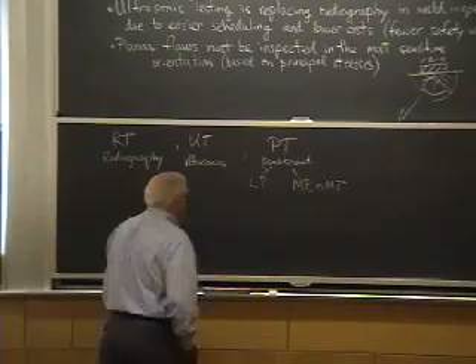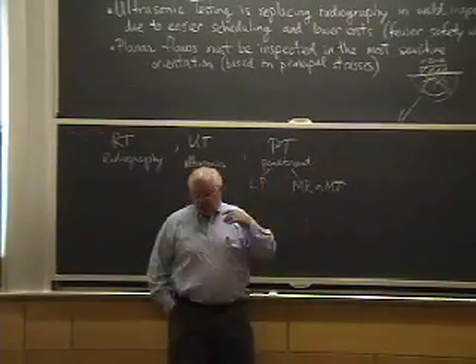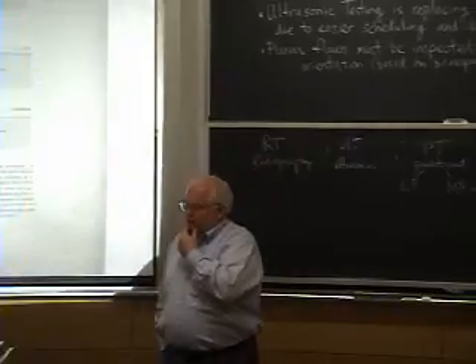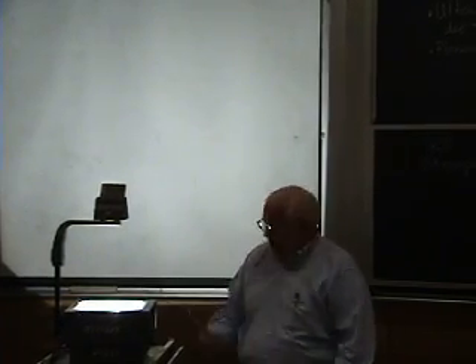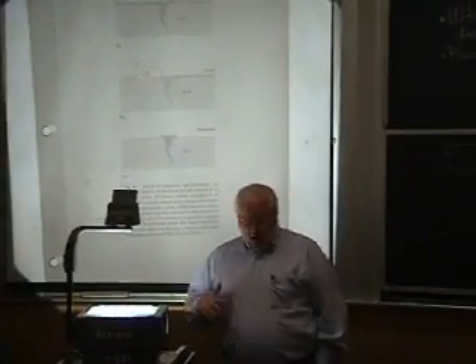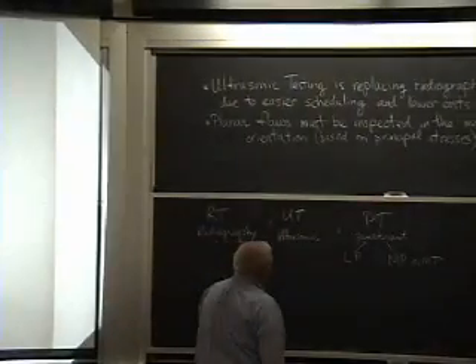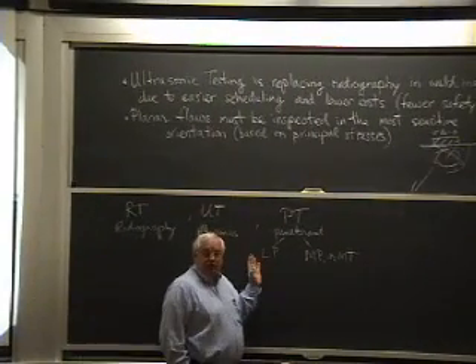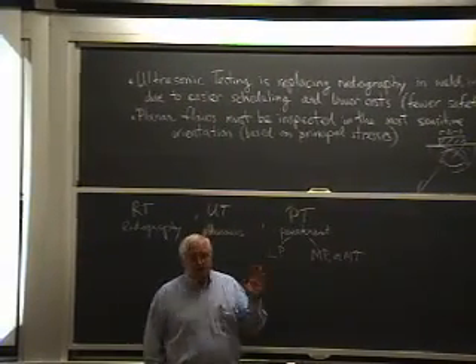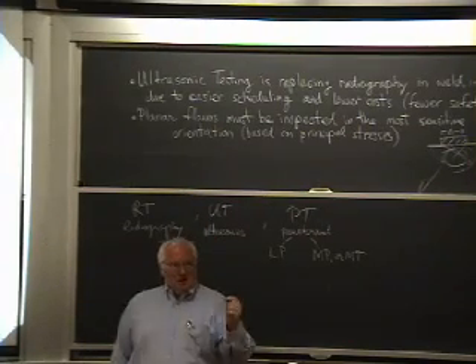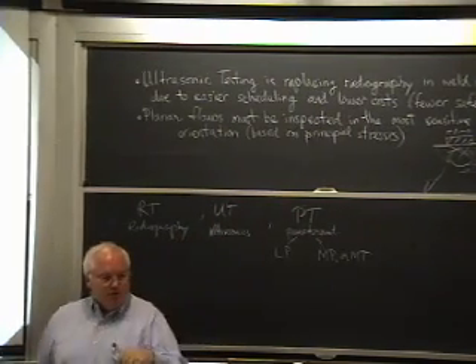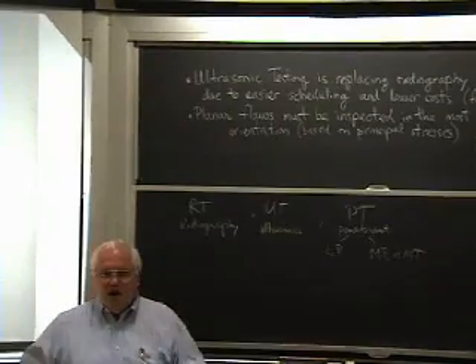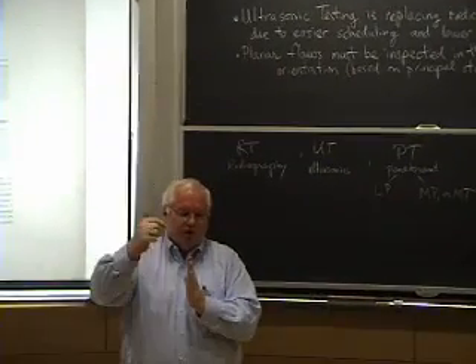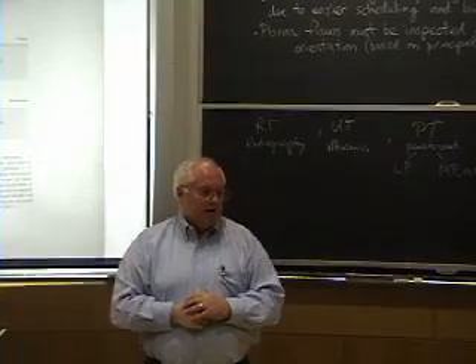So it gets a little fuzzy sometimes when people start using this type of notation, exactly what they're talking about. It's not generally too unclear. Let's talk about liquid penetrant testing. First of all, liquid penetrant testing can be used on virtually any material. If it's got a crack, and the crack comes to the surface, all you need to do is find a liquid that will wet the material and be pulled into the crack. The cracks are usually small, and therefore, if it wets, it actually will be pulled in by capillary attraction.